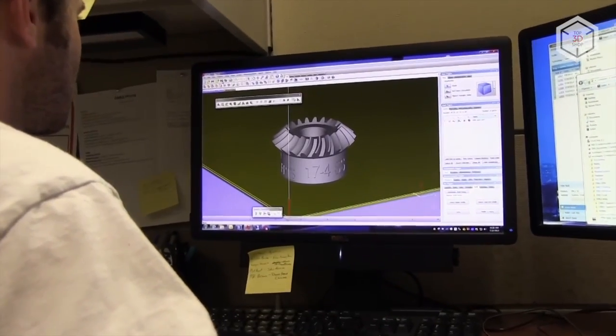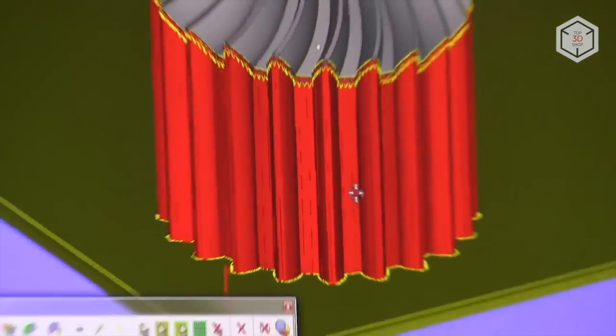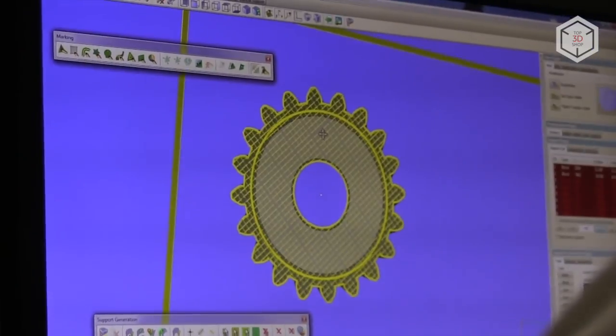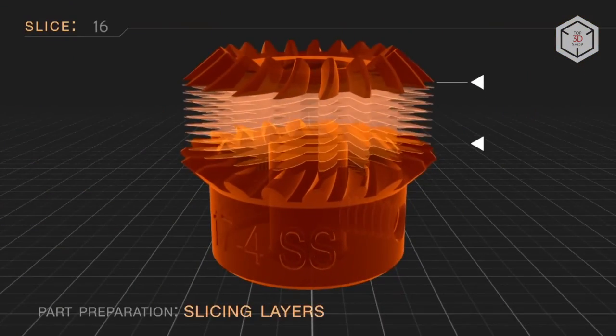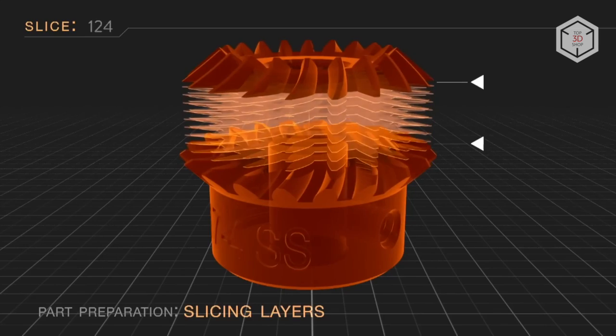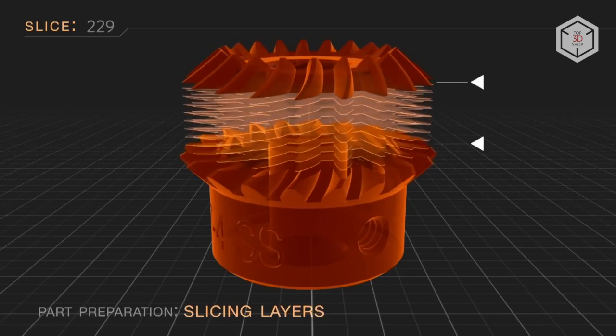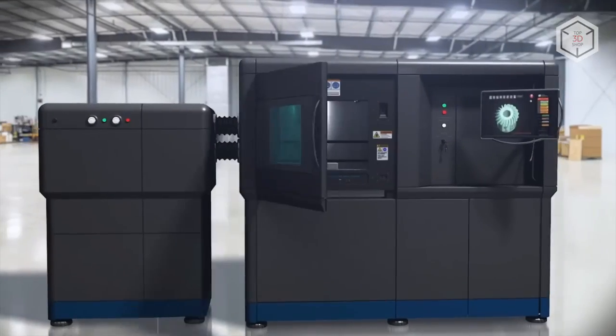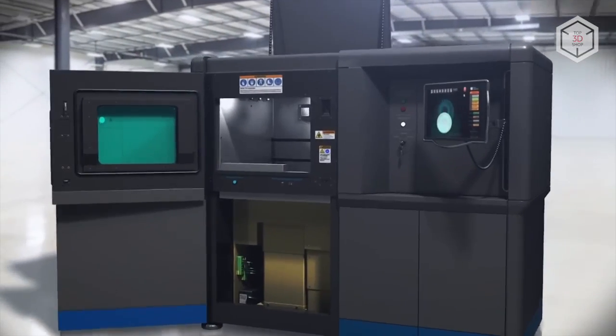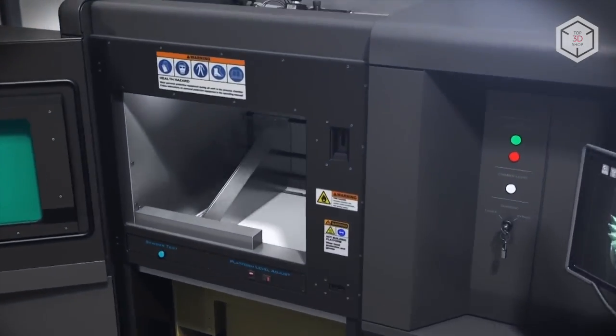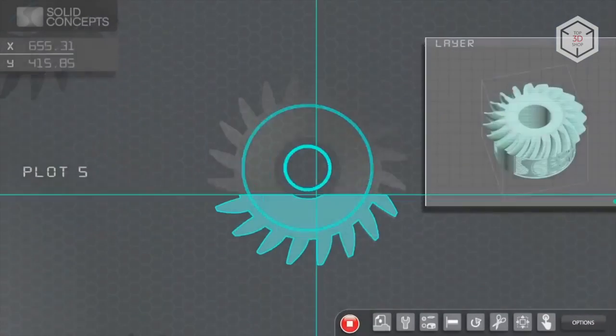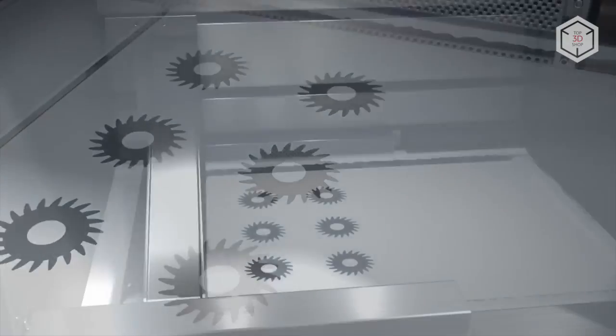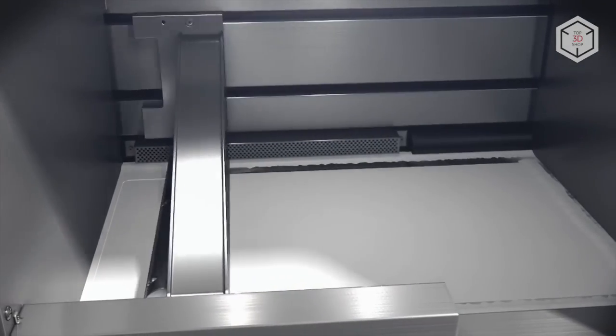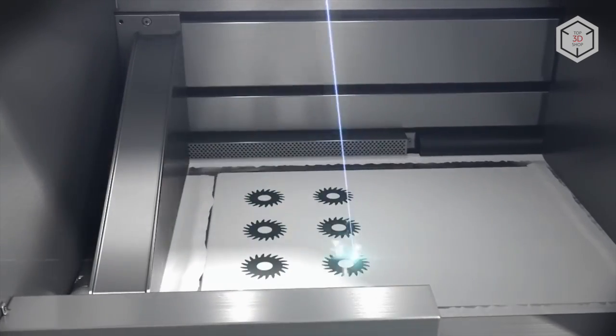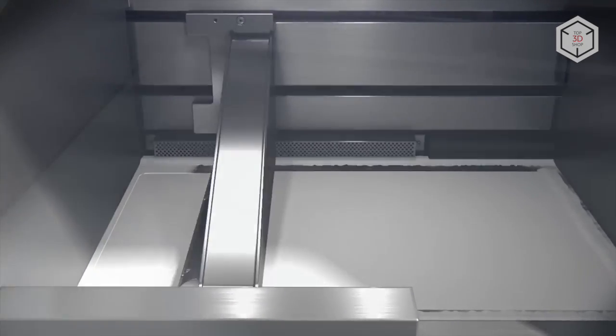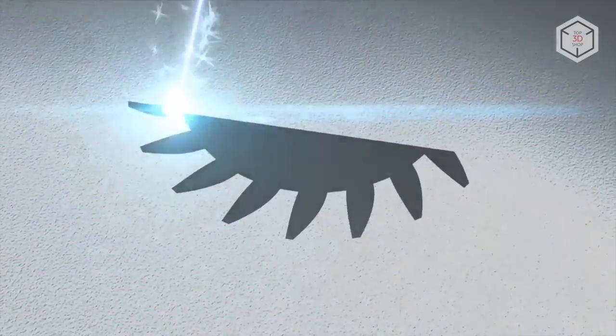Selective laser melting and direct metal laser sintering are the two most common additive manufacturing processes that use metal powders. Less common technologies for 3D printing with metals include laser or high-power electron beam additive manufacturing, as well as binder jetting, where the process of 3D printing is implemented by applying and binding of the metal powder layer by layer. The differences between SLM and DMLS relate to the method of binding the particles together. With SLM, the metal powder is melted down by a laser beam, while in DMLS, the powder particles are heated with subsequent sintering while avoiding the solid to liquid transition.